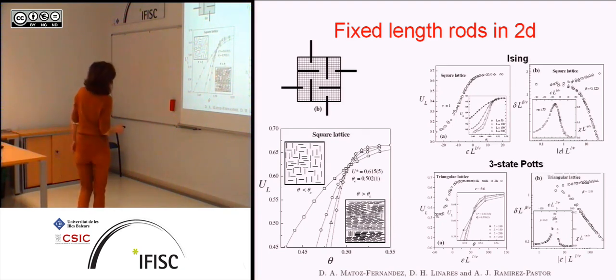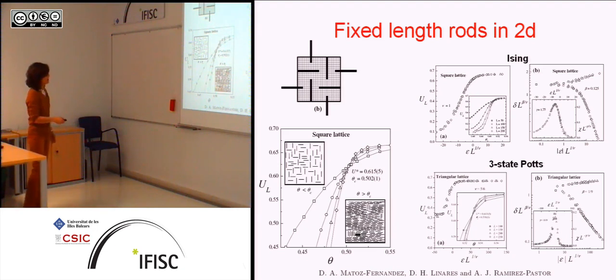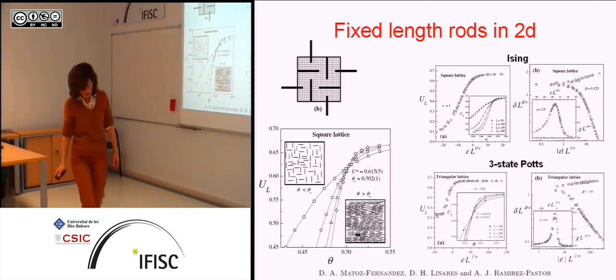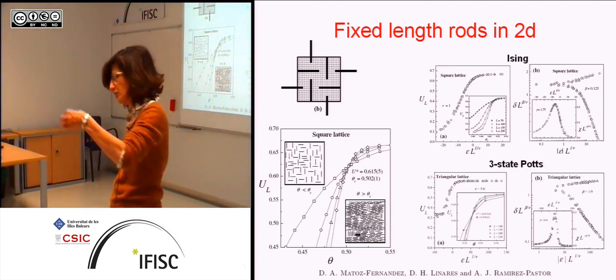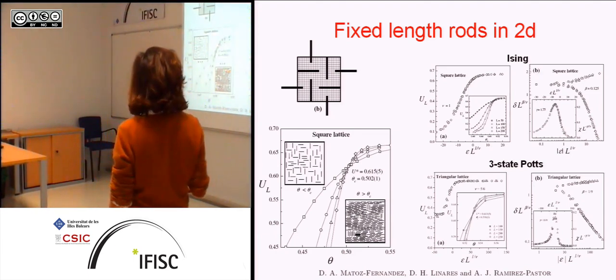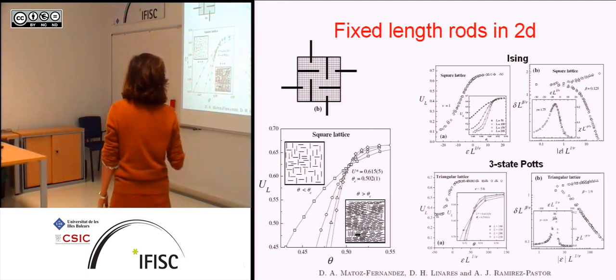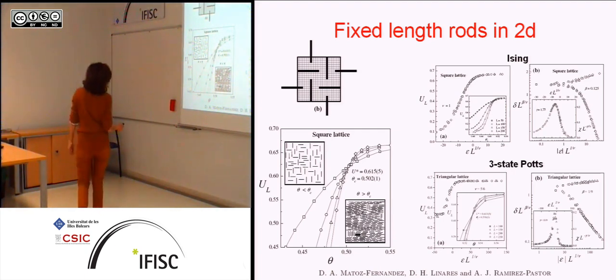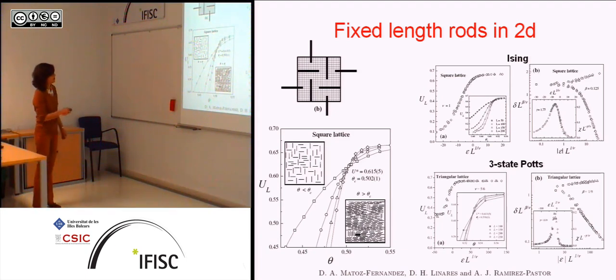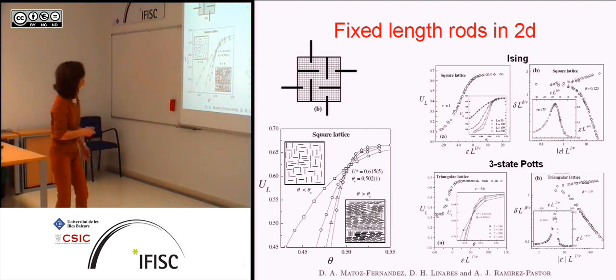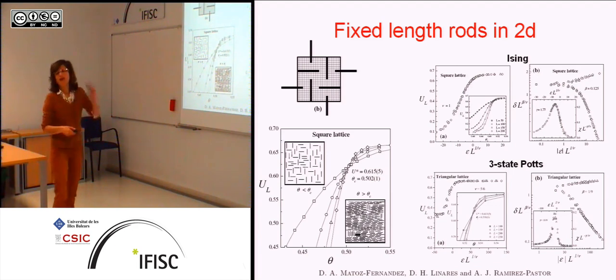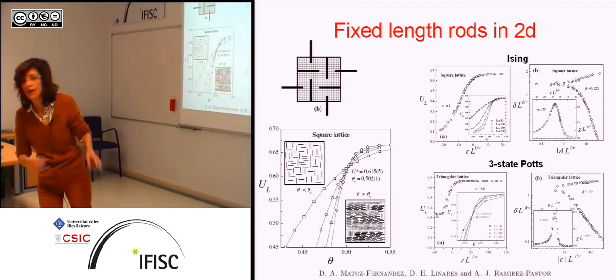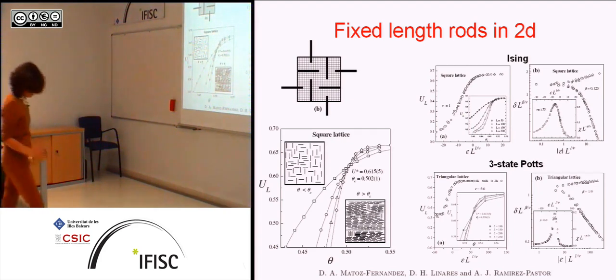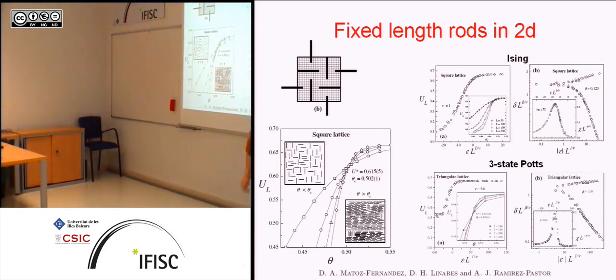And you see that these rods will align. You find an ordered phase at a certain critical density. These things are athermal, only excluded volume is the only quantity here. So as you increase the density of rods, the number of rods, they will have to pack, and they pack more efficiently if they order, so they order. And of course, if you ask yourself what the order of this transition is, it might not seem very obvious, but first of all, in two dimensions, this ordering transition is continuous. And on the square lattice, you really only have two states. So this is an Ising type transition. They actually measure the exponents using proper, quite standard now, techniques, and they found that these are Ising.